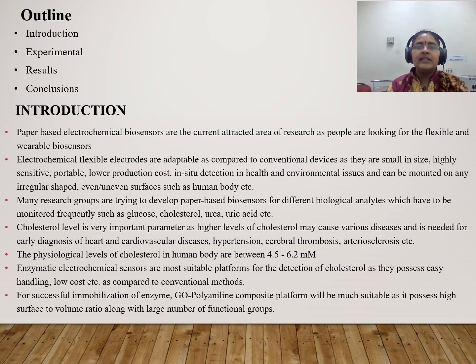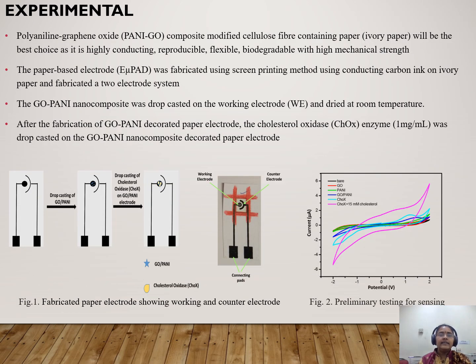Why have we used this? Graphene oxide has many functional groups attached to it, so that the enzyme can be easily immobilized on graphene oxide, and polyaniline is a very electroactive polymer, which can give very good electrochemical properties. Therefore the combination of this composite helps in getting a sensitive device. The experimental work carried out: the polyaniline graphene oxide composites were prepared.